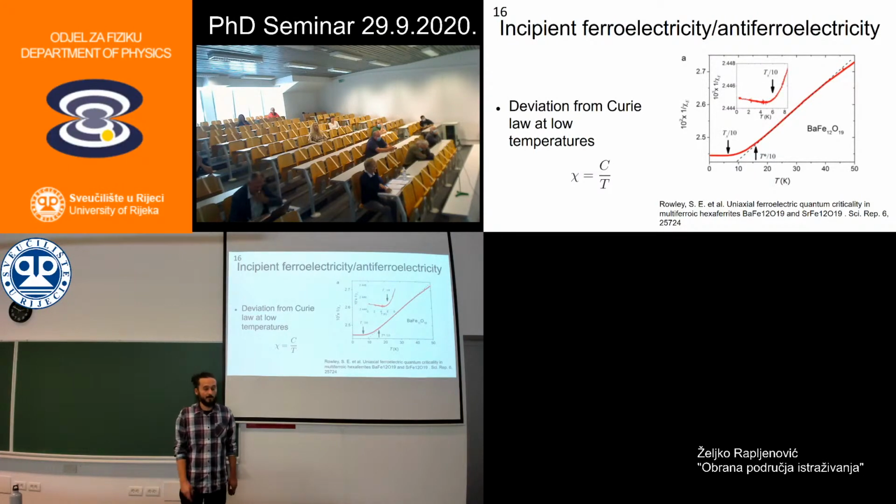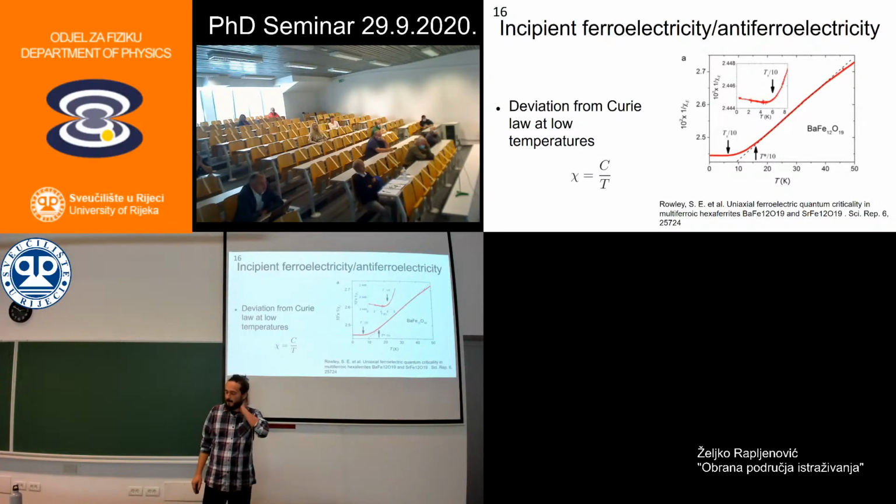Other people have also measured the electric response on the parent compound. The compound before had barium in some percentage substituted for strontium. They measured the inverse electric susceptibility versus temperature. And in this region, it follows the Curie law.